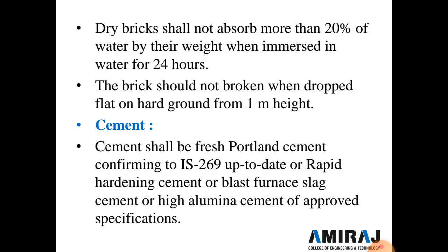And dry brick shall not absorb more than 20% of water by weight when immersed in water for 24 hours, and the brick should not break when dropped flat on hard ground from 1 meter height.